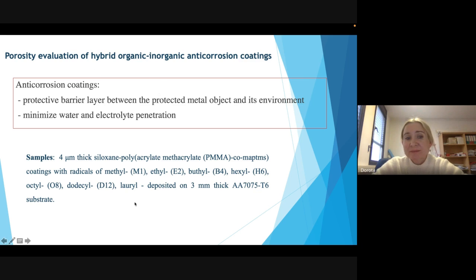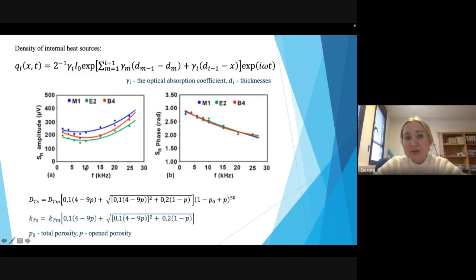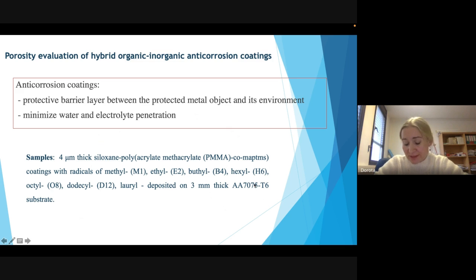layers that were made of siloxane materials, but we also examined how the porosity values change when we change the radicals. The radicals of our interest were from methyl to dodecyl and lauryl. So let's have a look. The sample of our interest was 4 micrometers thick, so it was necessary to perform the measurements at high values of modulation frequency, just to collect information only from our coatings without the influence of the metal support on which the sample was deposited.